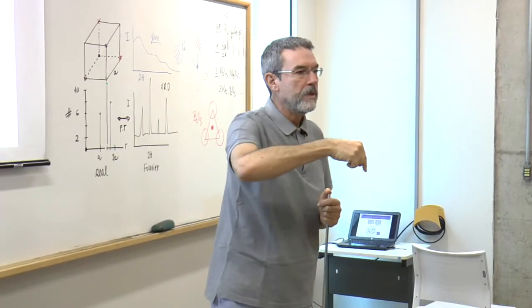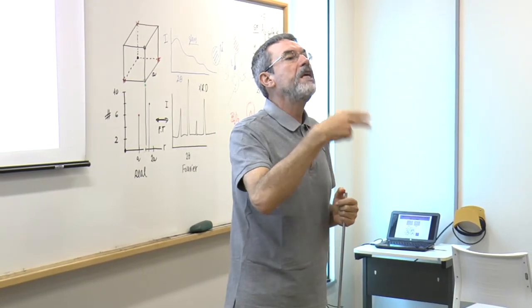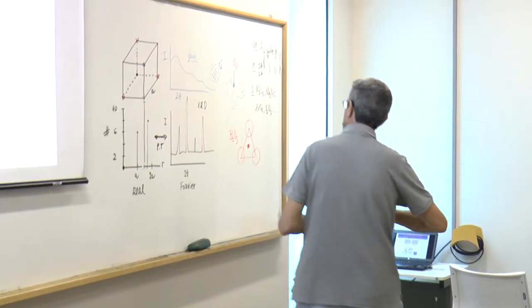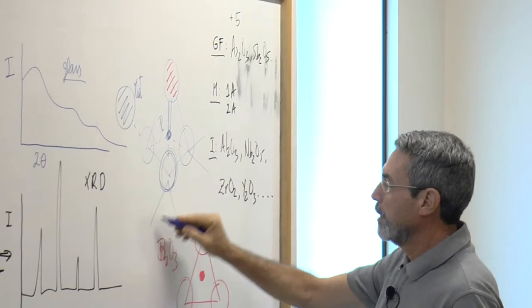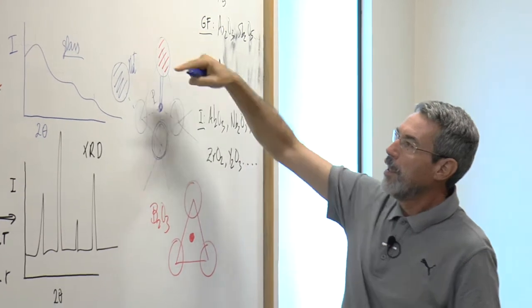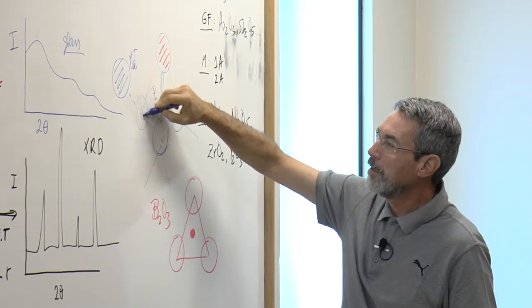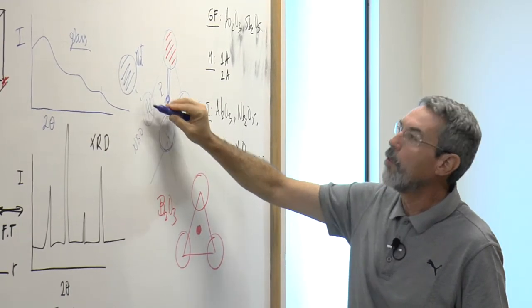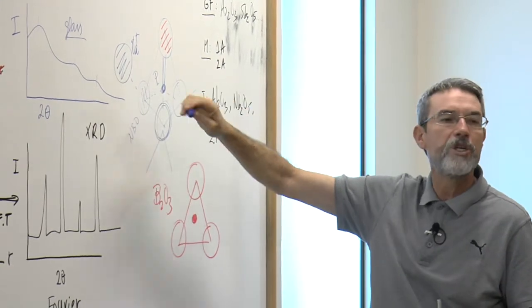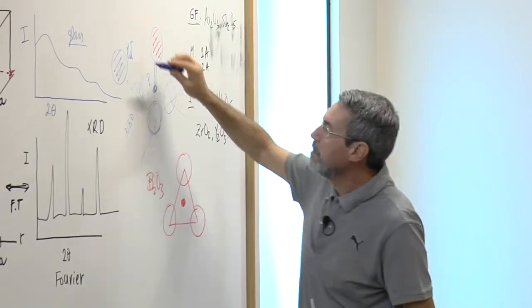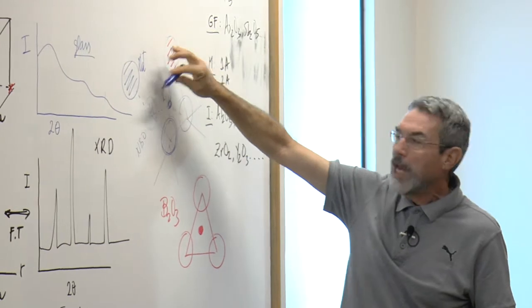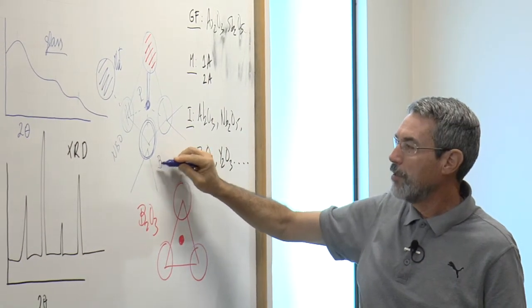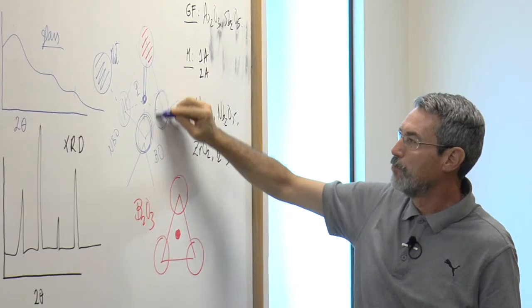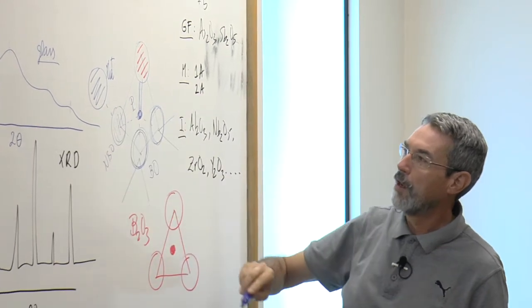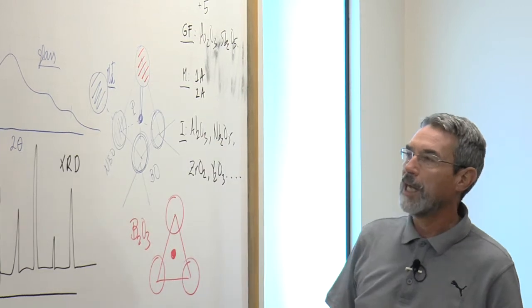When you add one atom of a modifier cation, that bridging oxygen, this one here, which is sharing 2 tetrahedrons, is a bridging oxygen. If I add sodium, I form a non-bridging oxygen. This is a non-bridging oxygen because, okay, it's still linked to sodium, but it's not bridging one tetrahedron with another tetrahedron. And this linkage here is weaker than this one here. This type of oxygen is a non-bridging oxygen, which is linked to a modifier cation, which can be lithium, sodium, or rubidium, or potassium, or anything.